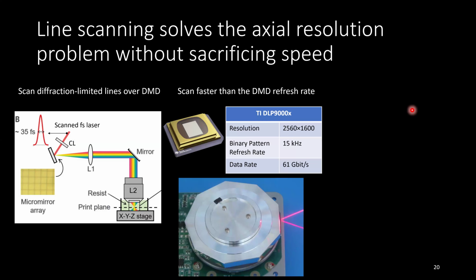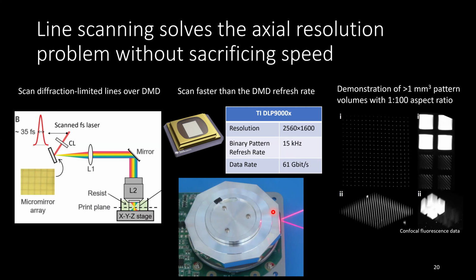But then as long as you can scan it across the DMD faster than the DMD can actually refresh based on the hardware, you can still essentially go at the full speed of patterning entire planes at a time. Yep. So these DMDs have a binary refresh rate of around 15 kilohertz, which is easily mechanically scanned with a polygonal scanning mirror. And so we've built these and have demonstrated very large volumes that maintain good resolution.